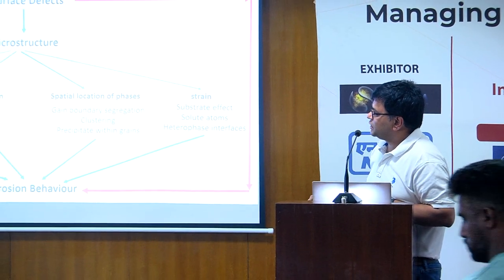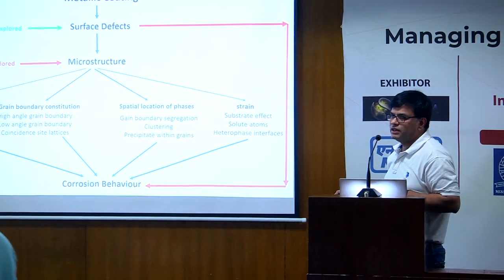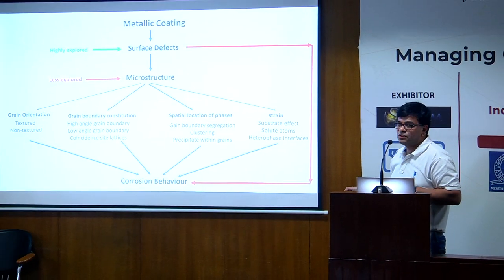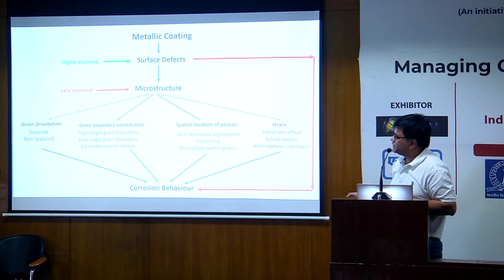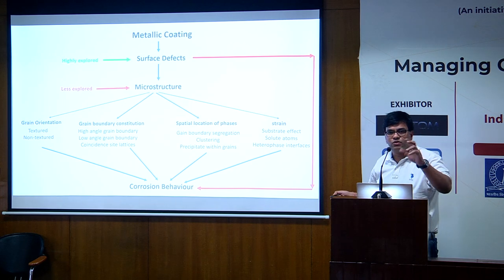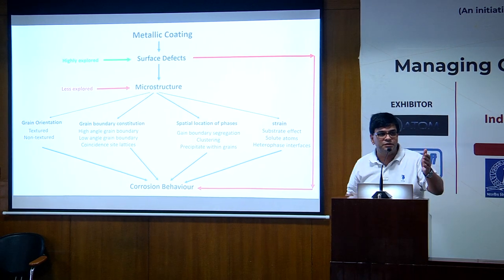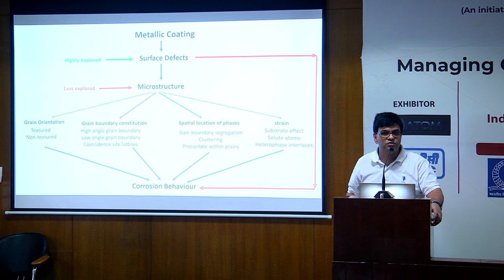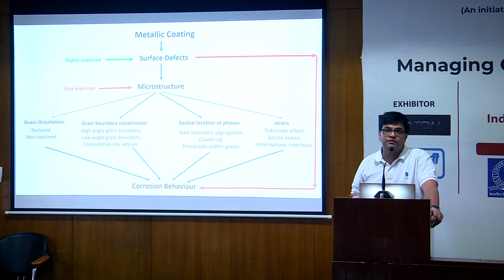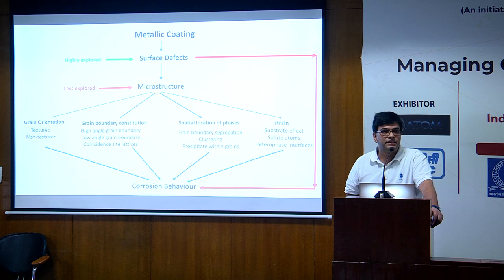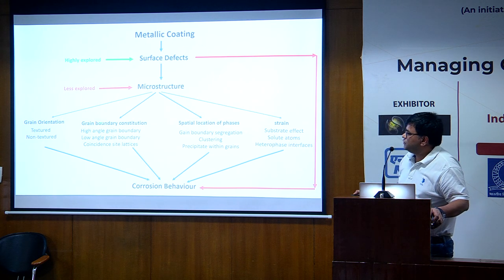And when you come to the microstructure, there are several parts which are very important. One is the texture of the coating, which is the grain orientation, how different grains are oriented on the surface. If you have a high energy plane, that leads to higher corrosion. For example, in an FCC structure, 111 is a low energy plane, and the other planes are higher energy than the 111 plane. Grain boundary constitution is also very important.